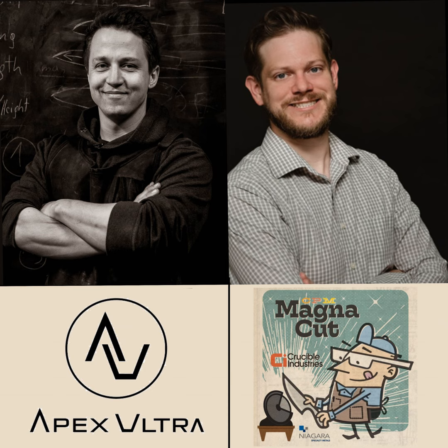Although, to be honest, I've had very nice etches on wrought iron by just dunking it for 2 minutes in ferric chloride and then rinsing it off and neutralizing afterwards. It all depends on how much of a contrast you want. Do you want the apex to be fully darkened? Do you want it a little bit more subtle? Which finish are you going for, basically? So I don't think there's a one-fits-all answer to this question, but these are kind of my approaches of thinking. The ferric roughens it up a little bit, gives it a little bit of depth, and then I wash it off, neutralize it, and then I put it into a slower, more selective etch to get a color contrast from the different steels.